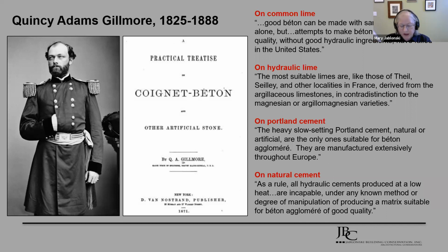He also felt that the quantity of water must not exceed what was barely sufficient to convert the matrix to a stiff, viscous paste. Then he noted that the matrix must be incorporated with the solid ingredients by a thorough and prolonged mixing, producing an artificial stone paste, decidedly incoherent in character until compacted by pressure, in which every grain of sand and gravel is completely coated with a thin film of paste. There must be no excess paste when the matrix is common lime alone, or with hydraulic lime. This precaution is less important, and with good cement unnecessary. He also noted the beton, or artificial stone, is formed through thoroughly ramming the stone paste in thin successive layers with iron shod rammers. And finally, he noted that the heavy, slow-setting Portland cements, natural or artificial, are the only ones suitable for beton aggloméré. He also noted that none of the cements made in the United States were capable of producing a matrix suitable for the beton aggloméré of good quality.